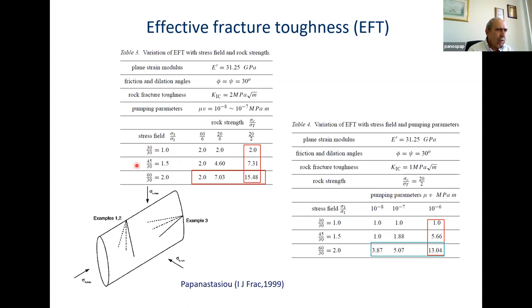And in the rows below, we have the stress field. The first row corresponds to the isotropic stress field. That will be the case when the fracture front propagates horizontally, let's say. The third row corresponds to an anisotropic stress field, and that will correspond to the case when the fracture front propagates vertically. In that case, you see from the calculated effective fracture toughness, we have high effective fracture toughness when the fracture propagates vertically compared to the case when the fracture propagates horizontally.